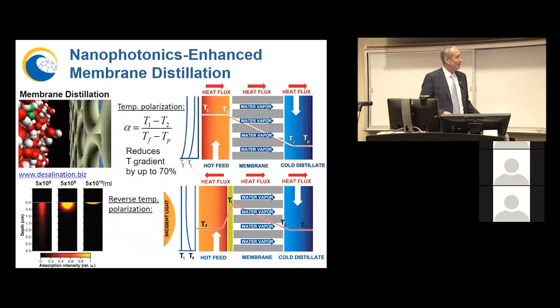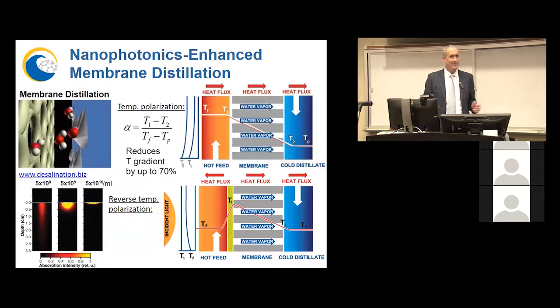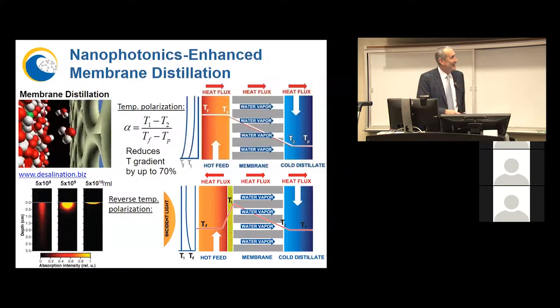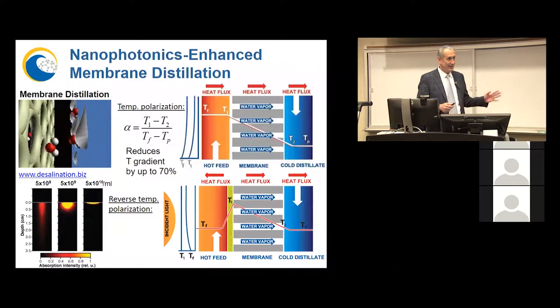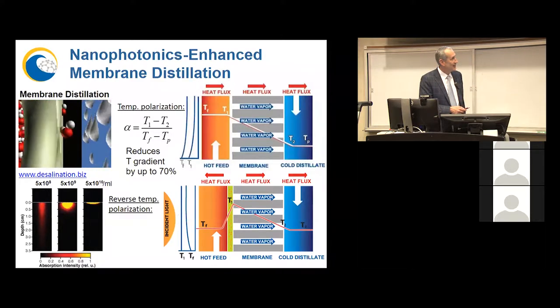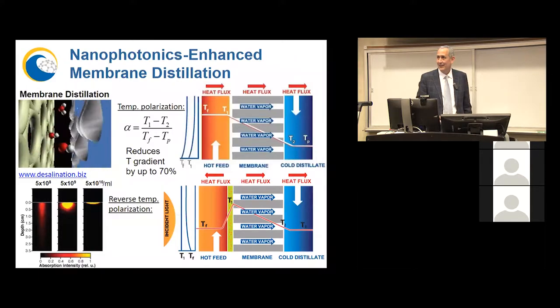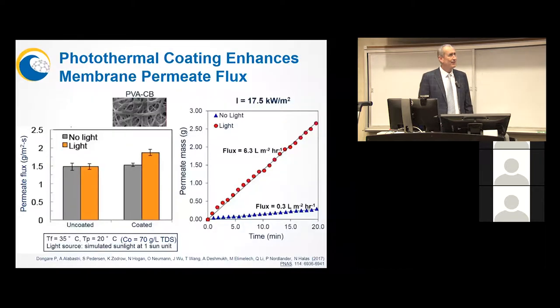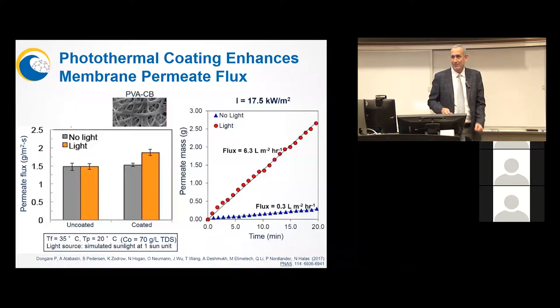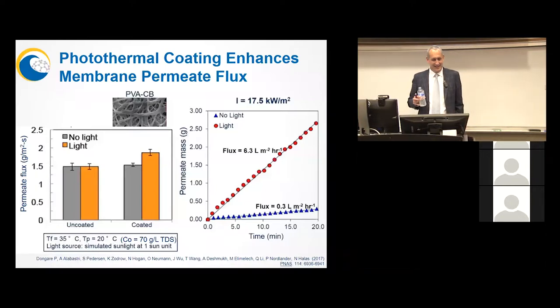But Chiling's idea was to make membranes in a plate and frame configuration that looks like a solar panel, and coat the upstream face of the membrane with these particles so that when they are irradiated by sunlight, you would actually reverse temperature polarization. You would increase the temperature gradient and therefore the flux. And in a first generation of membranes made of electrospun fibers coated with this carbon black, using an artificial temperature gradient of only 15 degrees Celsius, she was able to increase the flux by 30%. When she took those membranes outside and exposed them to the Houston sun, which is, you know, like today here, she was able to get about 60 times more distilled water produced in only 20 minutes when the membrane was coated. So it's very encouraging.